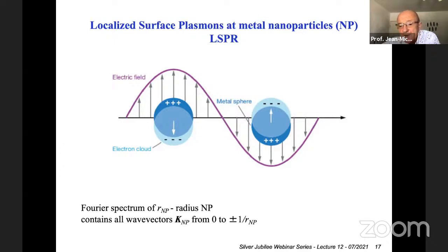If it is a plane surface, there are coupling conditions which require, owing to the dispersion of the energy of the electromagnetic wave propagating onto the surface of the metal, and for the conservation of the momentum of the light, a coupling technique, which people use, like either a grating or a prism, to couple an electromagnetic wave at the surface of a metal. This is not the case in a nanoparticle, because a nanoparticle is small enough to break the conservation of momentum, owing to a size that is way smaller than the wavelength of the light.